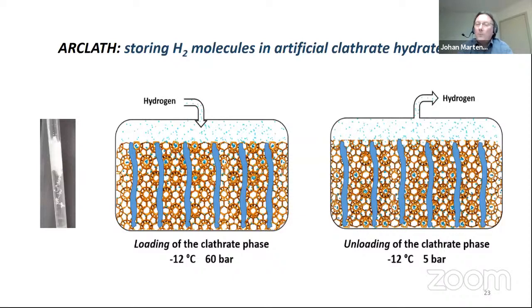What is this magic blue thing? Well, that's hydrophobic matrix material. And why hydrophobic? Well, in a hydrophobic environment, water tries to find other partners for binding. It is reorienting the hydrogen and the oxygen atoms, and that hydrophobic environment favors the formation of clathrates. And it's really spectacular how these clathrates form so easily when you simply pressurize such a tank. You fill it with liquid water, you cool, you introduce hydrogen pressure, and you get your hydrogen clathrates.